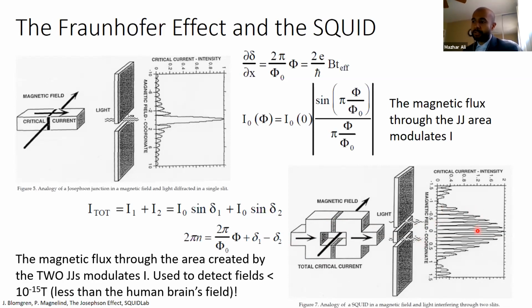So you get a faster oscillation that's, again, more sensitive to very, very small flux through, this time, not the JJ itself, but through the area defined by the loop of the two JJs. Now, how sensitive is this? It's incredibly sensitive, down to 10 to the minus 15 Tesla, for example. That's literally less than the human brain's magnetic field. So this is the basis for things like MRI. This is why Josephson junctions are very important.